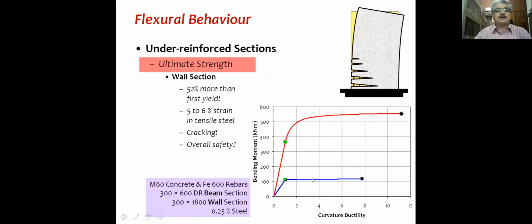Here you're seeing the moment-curvature, with curvature normalized in terms of ductility, of a 300 by 600 reinforced section and a 300 by 1800 wall section. Needless to say, the wall section has higher capacity, which is okay. But the interesting thing to note is the difference between the point where the first layer of steel starts to yield and the secondary compression failure point. This margin for this particular example is 52%. This will vary depending on the percentage of steel, the grade of concrete, the grade of steel, the dimensions of the wall, and so on. But what is being seen is that this margin can vary anywhere between 10, 15% to 50%.